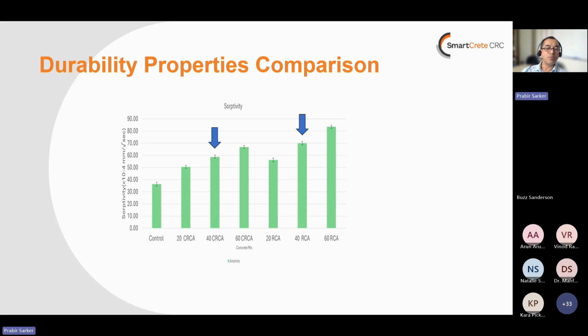Here is a comparison of the sorptivity. So we see a similar trend to what we saw before. This is the control concrete, 40% CRCA and 40% C&D waste aggregate concrete. So we can see that with the CRCA, the performance is actually better than the 40% C&D waste aggregate concrete.